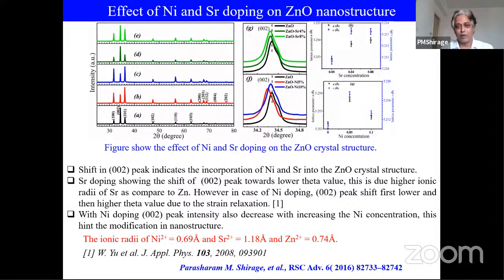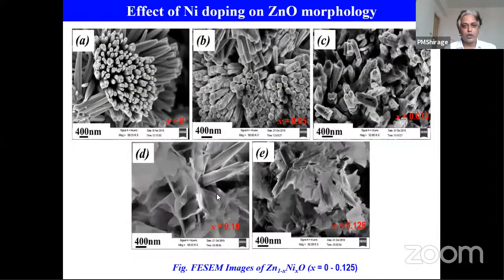In the case of nickel, this black curve again is zinc oxide, and the red and blue curves represent 5% and 10% replacement of zinc with nickel. This is unsystematic. First it is decreasing, then increasing. Why? It should decrease because we are replacing zinc with nickel, and the ionic radius of nickel is smaller than zinc, but it is first decreasing, then increasing. This is not only because of replacement of the material; some modification is there, and other stress, strain, relaxation also plays an important role. So why is the lattice constant not continuously decreasing or increasing? For that, this is the important information.